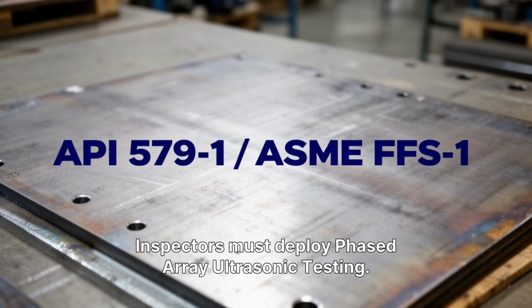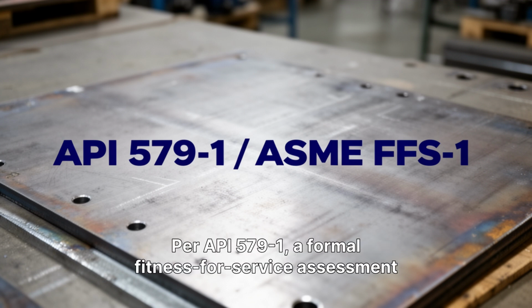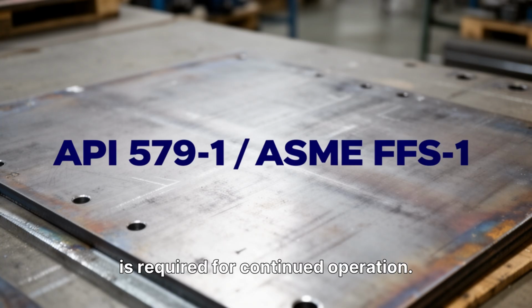HIC forms internally within carbon steel, typically near sulfide inclusions in the base metal. It is invisible from the outside and develops in wet, sour service environments. Look for stepwise crack morphology parallel to the plate direction. Inspectors must deploy phased array ultrasonic testing per API 579-1. A formal fitness for service assessment is required for continued operation.